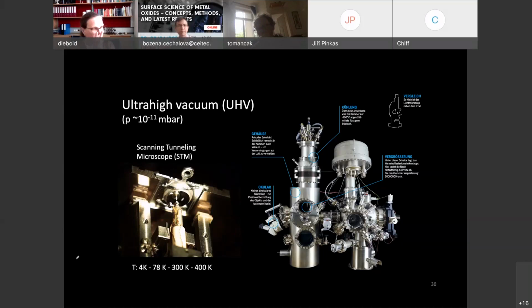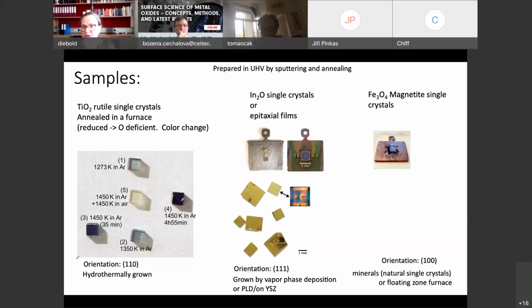Okay, before I go to scanning tunneling microscopy, let me talk a little bit about samples. I talked about this indium oxide already a little bit. I told you it's optically transparent. Actually, it's a little bit yellowish. And the reason is just that even though it has a 3 eV band gap, there is some Urbach tail there. So there's some optical phonon excitation. Well, we're not going into these details. But anyway, you can still look through it, still pretty shiny. So these are indium oxide single crystals.